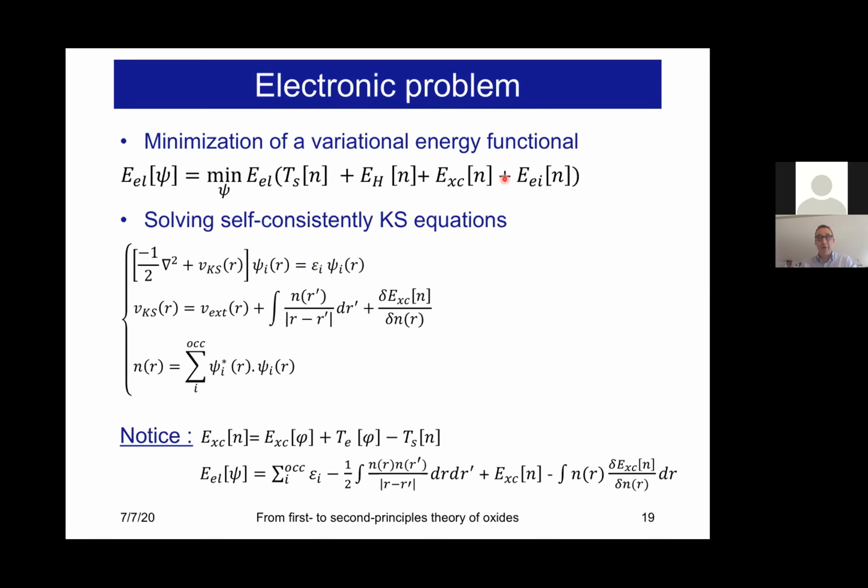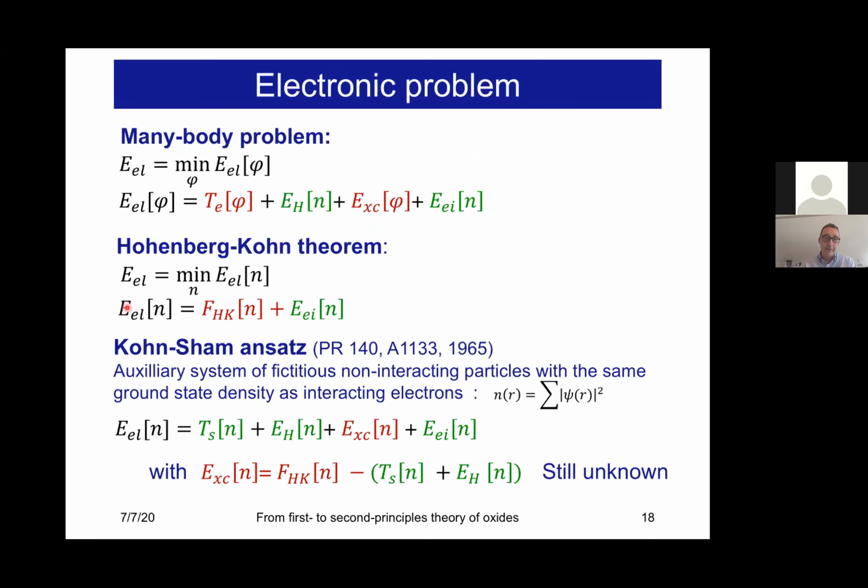So basically, the total energy that we compute is not simply the sum of the eigenenergies of the independent particles, but it includes some corrections here. So basically, the auxiliary system of non-interacting particles that is put here is just a trick to access the total energy, but within density functional theory, as you have seen from my construction here, I am really accessing the same energy as the one of the many-body problem. It will be exactly the same if I know what to put here.